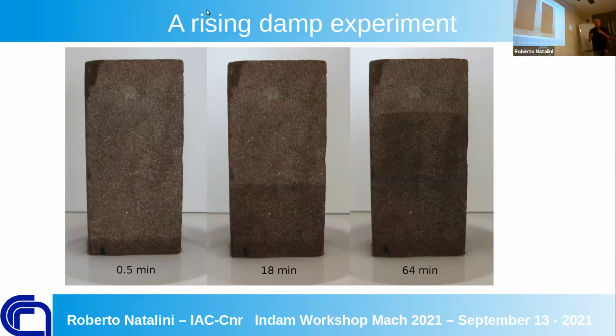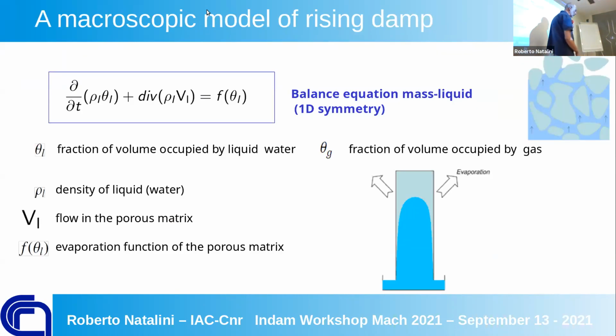You take a brick, you put this brick in water, and you have this rising damp because of capillarity. And after, here I can see 0.5 minutes, 18 minutes, 64 minutes, and so on. I want to understand this kind of phenomena because they are typical of what happens when you look at a lot of monuments, buildings, artifacts, cultural heritage.